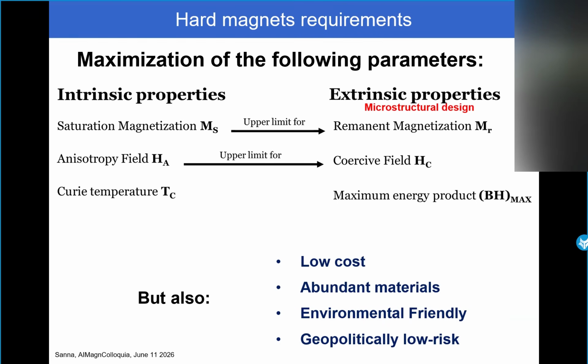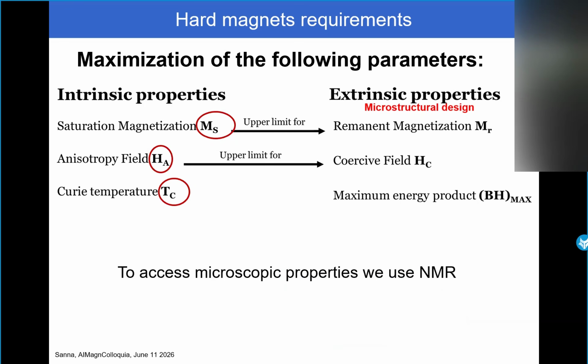And regarding intrinsic versus extrinsic properties, we can say that for real applications, we need to improve these extrinsic properties. But the upper limit of these parameters, such as remanent magnetization and coercive field, are respectively the saturation magnetization, which is related to the ordered magnetic moment, an intrinsic parameter, and the anisotropy field, which depends on the ability that we have to move the magnetization in the system. And in order to study these intrinsic parameters, which are the upper limit for the extrinsic parameters, we are trying to use nuclear magnetic resonance.